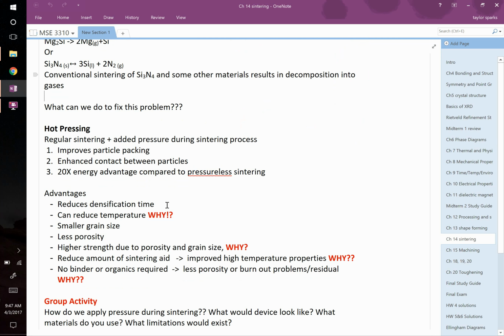If particles are touching firmly with one another, then the diffusion, or whatever the transport mechanism is, is going to work better. And you typically get like a 20x energy advantage compared to pressureless sintering. What do we mean 20 times better in terms of energy? Well, if you fire something and you have to take it up to 1500 degrees and leave it there for 10 hours, think of all the energy that's going to go into that. That's a pretty enormous amount of energy probably. It depends on the size of your furnace and all that, right?